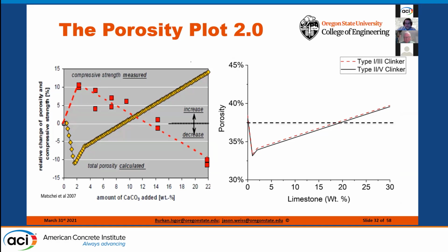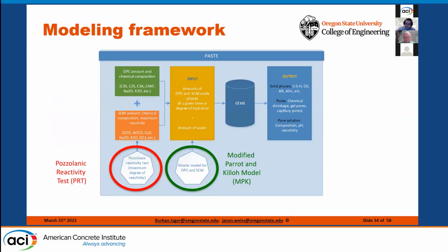Now, how do we use this to predict some of the results that we're talking about here? So again, remember, this is that plot from Matschei and Herfort, where they said initially we're going to see a decrease in the porosity of the system. When we do this in the model, we see that exact same decrease, right? We see a slight increase in the porosity, and again, we take this out. Now, we go out to a value of about 18%. And part of the reason is they didn't actually start at 0 when they ran some of these calculations, which is kind of interesting. But we see a very, very similar type of behavior here. So this is telling us that at least for the standard system, we're on the right path.